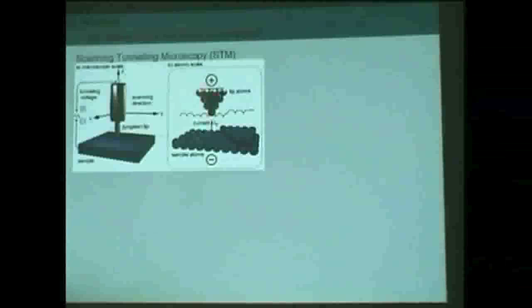So we need to put the tip very close to the surface. Since this current is very sensitive to the distance between the tip and the surface, if you keep scanning the surface with the tip and measure the current as a function of position, you can get an idea of the topography of the surface. This is the principle of scanning tunneling microscopy.